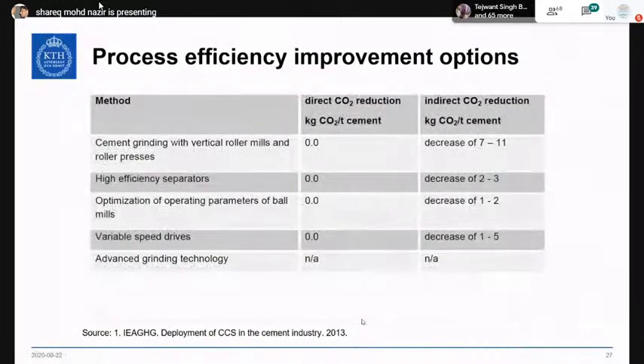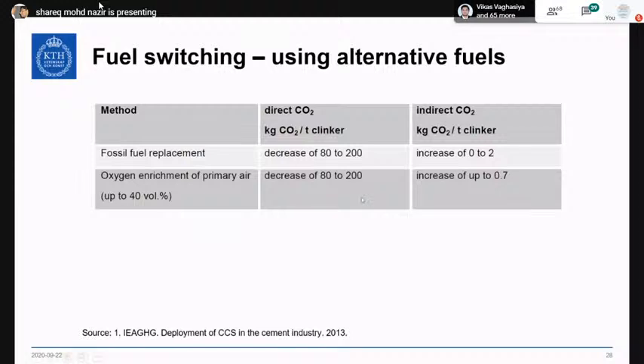Speak about the process efficiency, the other process efficiency improvement options: none, but then indirect CO2 reduction, again, very little, 7 to 11 kgs, 2 to 3 kgs, 1 to 2 kgs, 1 to 5 kgs, not much. We speak about fuel switching options in the cement plant. If you replace the fossil fuel, coal, with biomass, for example, we could decrease between 80 to 200 kgs per